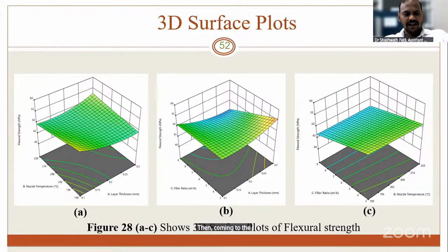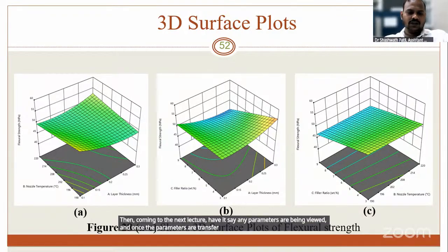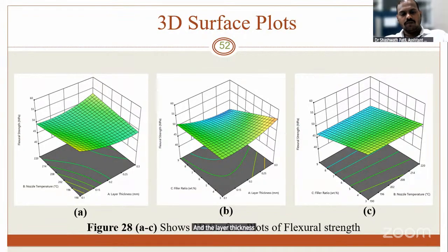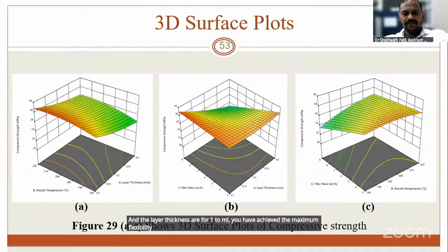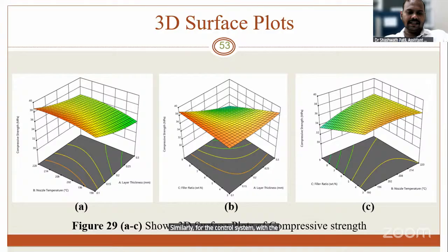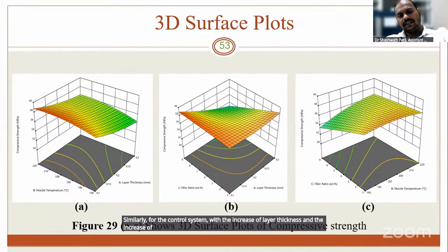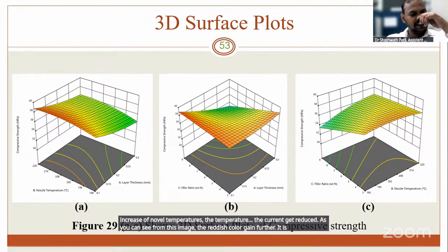Then coming to the next plot, two parameters are varied and one is kept constant for the flexural strength. Here also, keeping the nozzle temperature at 210 degrees and the layer thickness at 0.2 mm, we achieved the maximum flexural strength. Similarly, for the compression, with the increase of layer thickness and nozzle temperature, the strength is reduced. As you can see from this image, the reddish color zone shows where the strength is reduced.